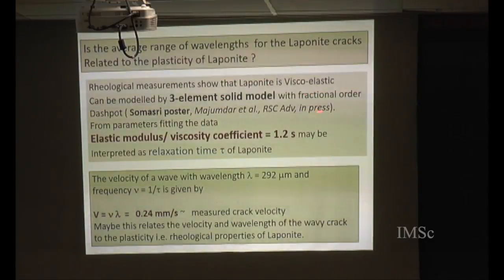This is a 3-element solid model, and maybe you have seen it in the poster. And from the parameters of the model, which give the best fit to the experiment, we have the elastic modulus and the viscosity coefficient. If we take the ratio of those two, we get some quantity of the order of time, some sort of characteristic time, which comes out to be 1.2 seconds. If we interpret this as the relaxation time of Laponite, which is a characteristic of its viscoelastic nature or its plasticity, then a very simple calculation,